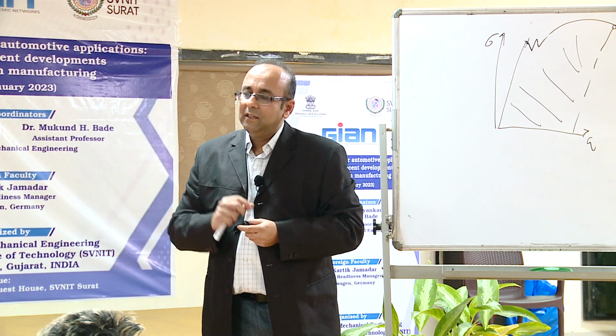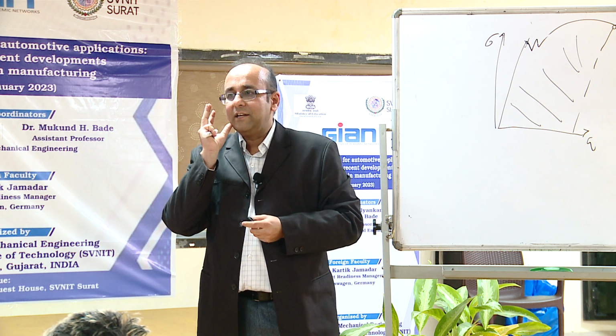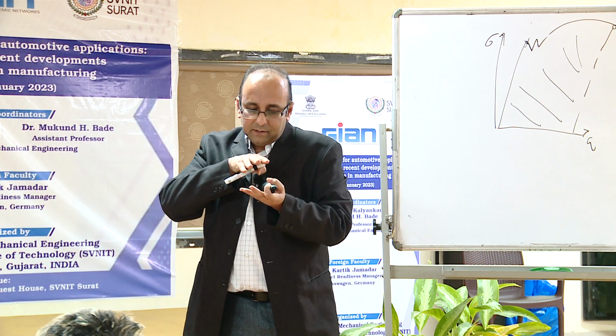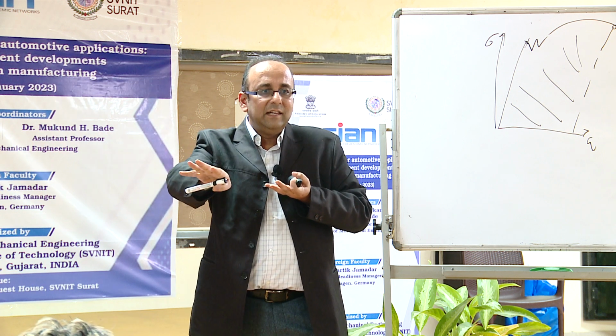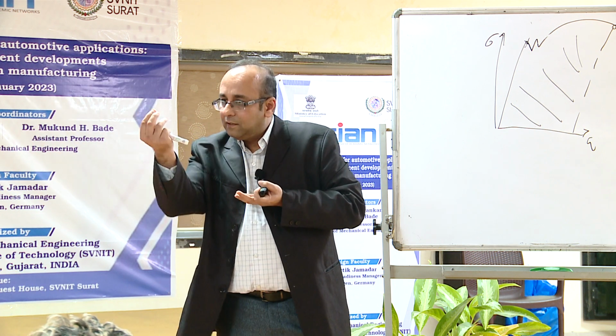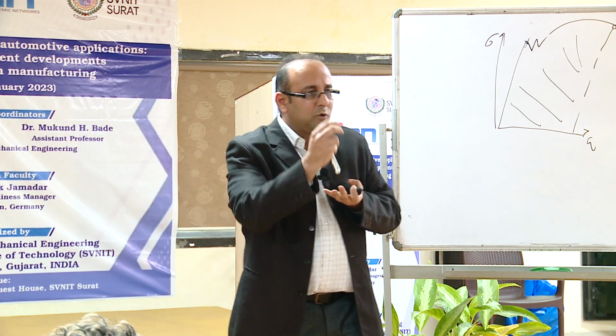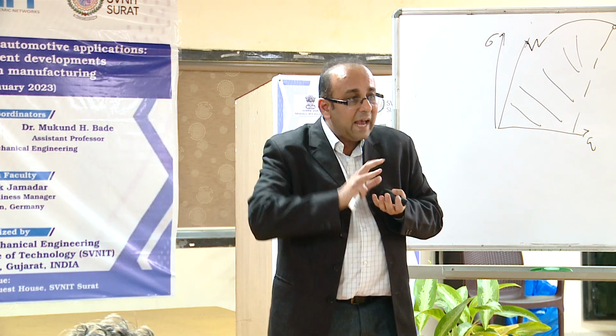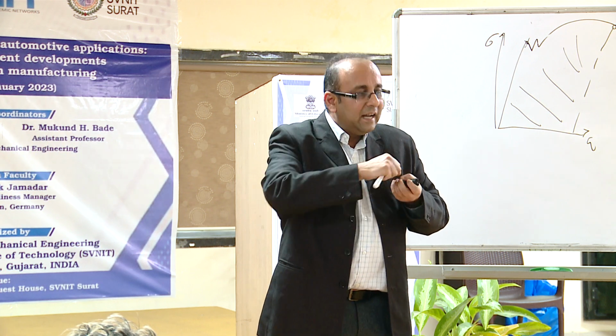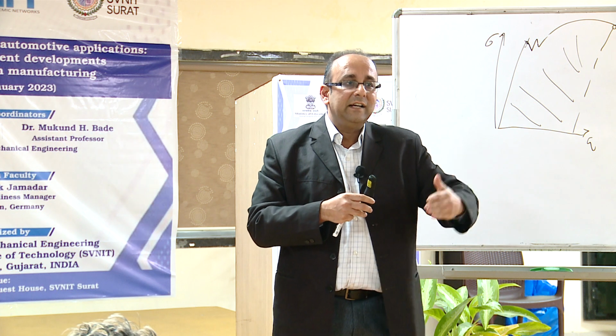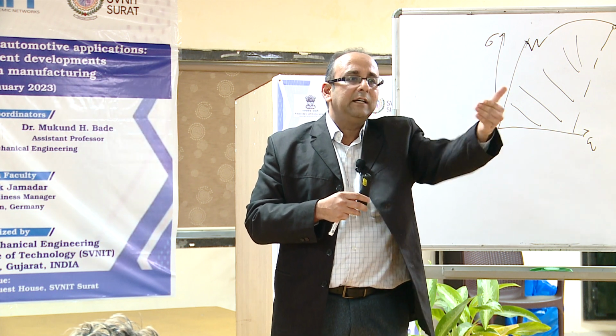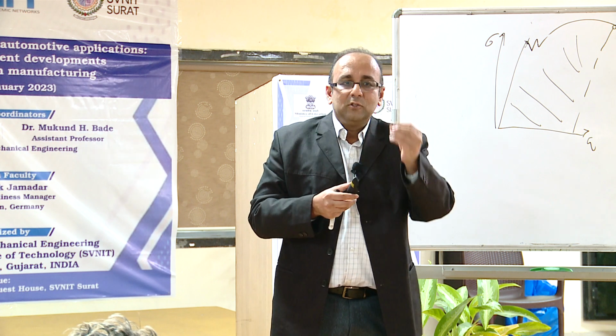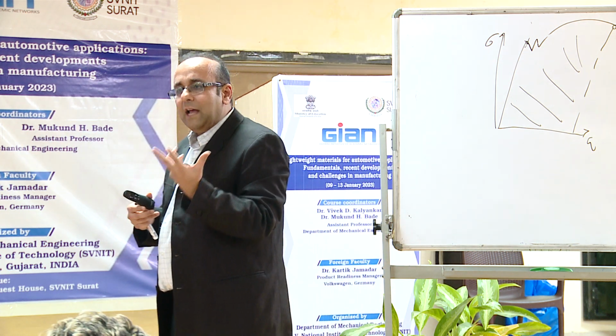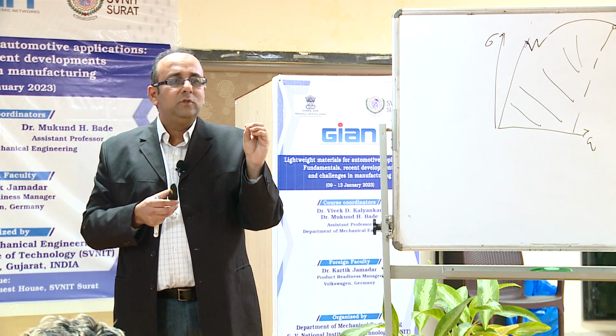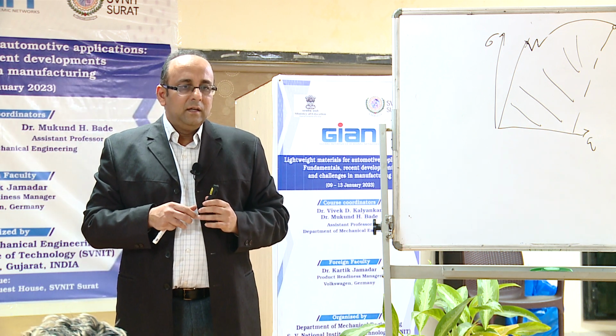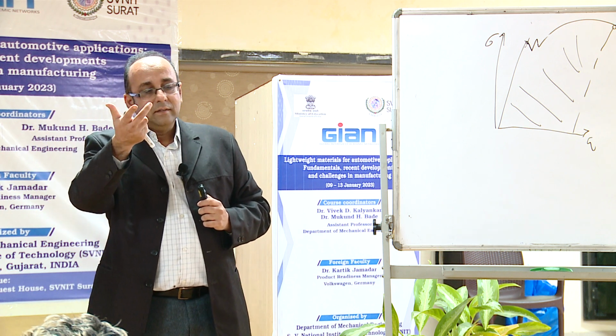What is bake hardening? You add some nitrogen inside your crystal. So what is happening? The elements will not be able to glide easily because there is some kind of resistance coming from the alloys. Small alloy, carbon, nitrogen. But then you give some energy in terms of heat, and then it can be formable. So basically you are creating strength by giving 180 to 200 degrees centigrade, which you call bake hardening. So bake hardening is nothing else but a low alloy steel where you use alloys like nitrogen and carbon.